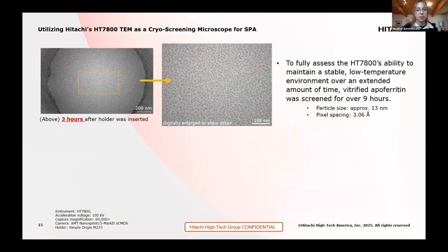So the first thing I wanted to look at is the ability to hold these conditions at stable and low temperatures. And so the first sample that I used, very classic standard for cryo-EM, is apoferritin. So here, after 3 hours after the holder was inserted, you can see we have very nice contrast, very nice resolution of apoferritin. These are roughly around 13 nanometers as a particle size.